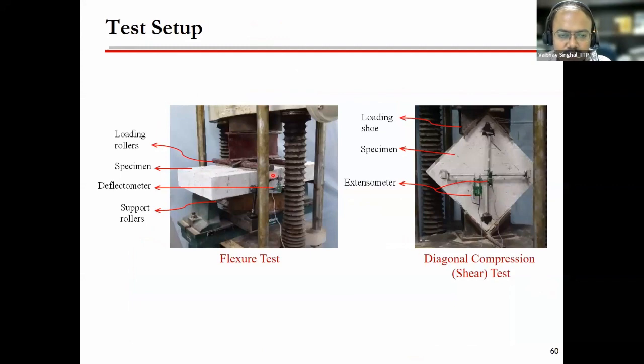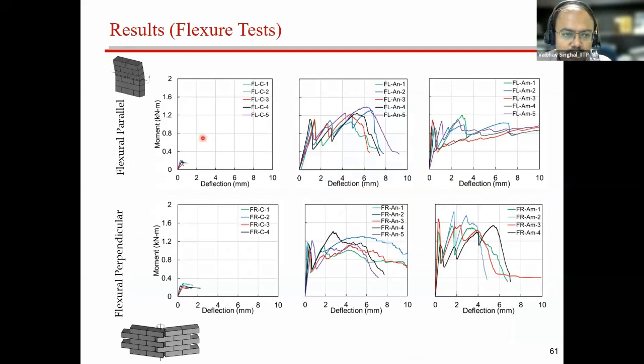These are the test setups. This is for the flexure test. This is for the diagonal compression test to find out the shear strength. And these are the responses of the flexure test. The first one is for the control specimen. There was no strengthening, so it was expected that the control specimen would have very low capacity. Compared to the control one, both strengthening techniques, where AN is for anchor and AM is for adhesive mortar, were good. Both gave nearly the same improvement in flexure strength, both perpendicular and parallel.